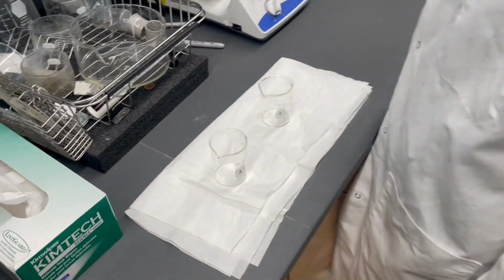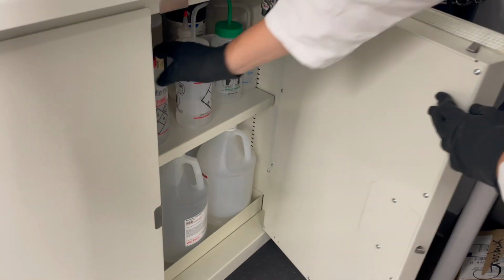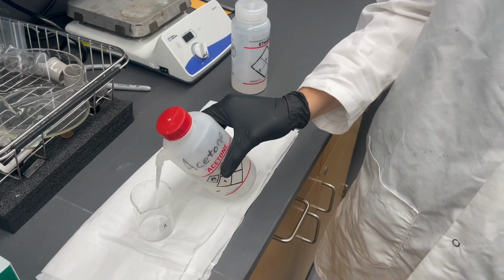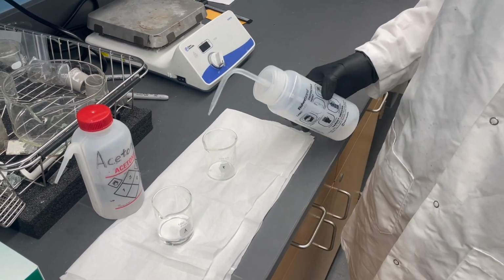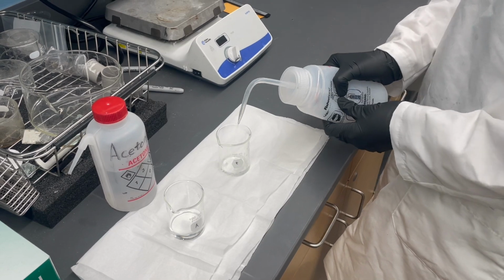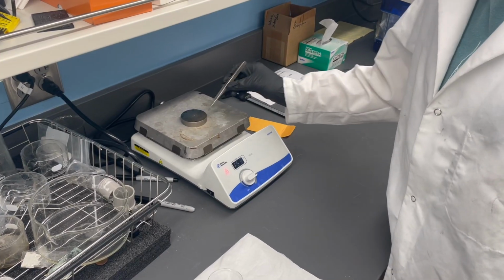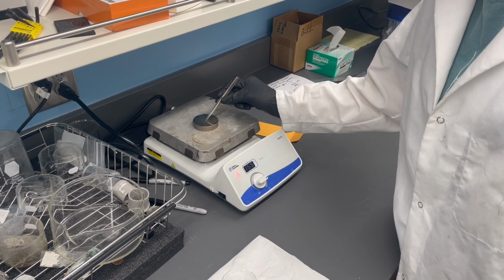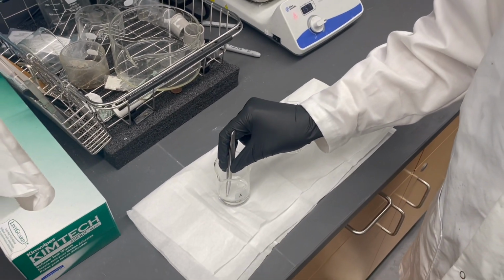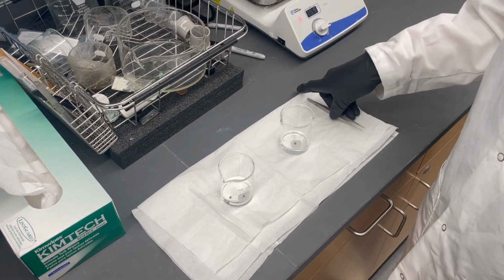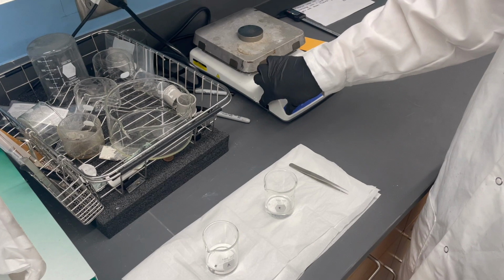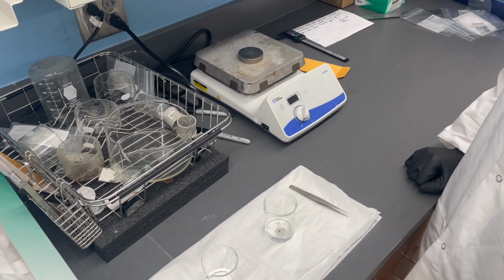Now we will prepare for final cleaning. Lay out the beakers labeled A and E. In the flammable cabinet, take out the acetone and ethanol. Fill small amounts of each in their respective beakers. After confirming the sample has a mirror finish, heat the polishing fixture to melt the crystal bond. Using tweezers, gently remove the sample and place it into the acetone beaker. The acetone will remove any residual crystal bond on the sample.